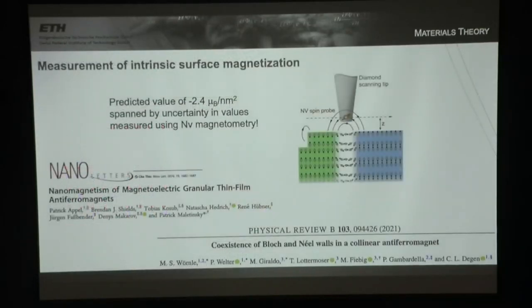And this was measured using NV magnetometry, which, I don't know, is anyone here doing NV magnetometry? It's a very difficult measurement to interpret. One measures a field. One has a little magnetic sensor in a tip from a nitrogen vacancy in diamond. One measures a field, and then one has to extract from that field what was the surface magnetization that caused it. But the range of values spanned by the uncertainty in these measurements includes minus 2.4 Bohr magnetons per square nanometer, and they have the correct sign. So we were very excited about this.